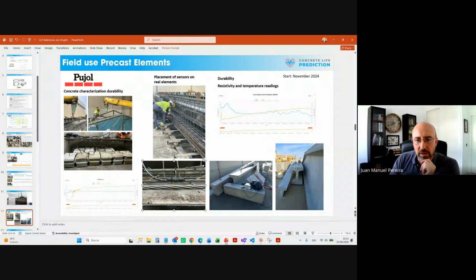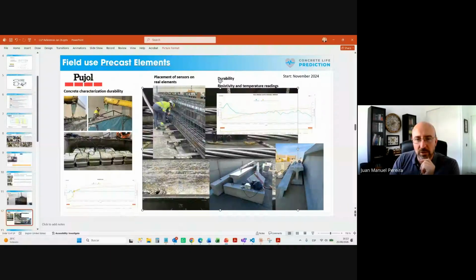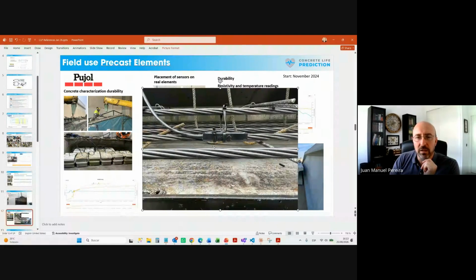You see here how we tie the sensor. Sorry, let me pull this up. Okay, so how we tie the sensor to, in this case, it's not a rebar, it's a pre-stressed tendon. So to measure, because this is the most critical part for durability, we measure the cover here, and we see how the chlorides or carbonation ingress to the passivated element, which is critical because this is pre-stressed. Okay, so this can be applied also in the factories.